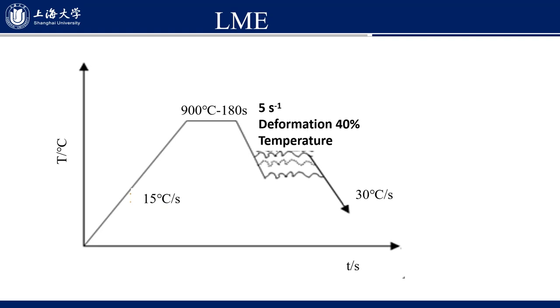The specimen was first heated at 15 degrees per second to 900 degrees C, kept for 3 minutes, and then cooled to the deformation temperature, deformed 40% with a constant deformation rate of 5 per second, and then cooled to room temperature at 30 degrees C per second.